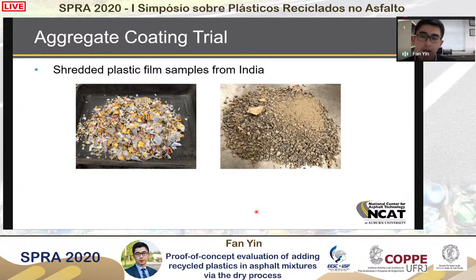We also looked at an additional sample. This is actually the real sample that we got from our contact in India. In this case, I would not call this fully processed plastic. This is pretty much like a shredded plastic film. And then we did the same thing with dry mixing, but I don't know if it is clear from the picture on the screen right now.